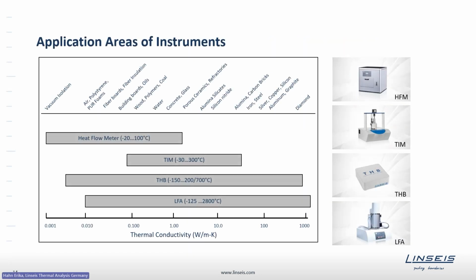This slide should give a short overview of the thermal conductivity and application range of the different instruments. There you can see that the laser flash and the transient hot bridge method cover almost the complete thermal conductivity range. Also, they offer a very broad temperature range, up to 700 or even up to 2800 degrees Celsius. The TIM tester and heat flow meter are a little bit limited regarding the thermal conductivity range as well as the temperature range. But depending on the application, one of those tools might be the ideal one, the best fitting one.